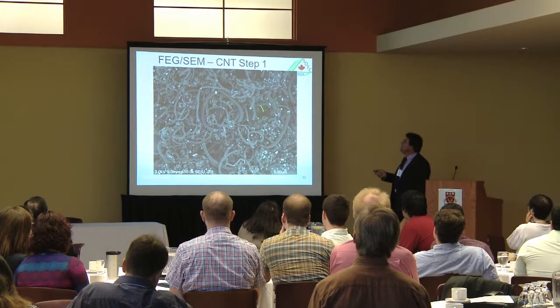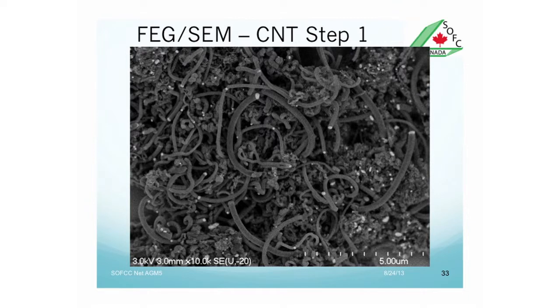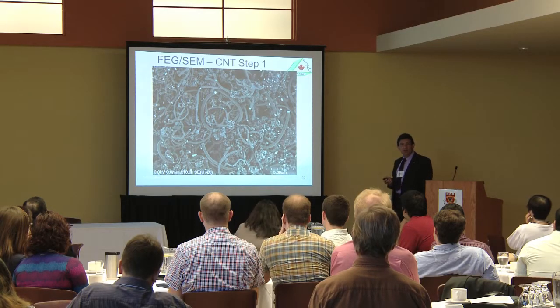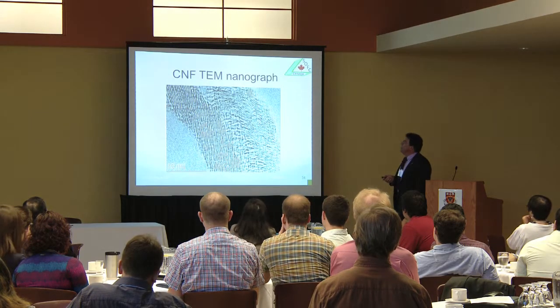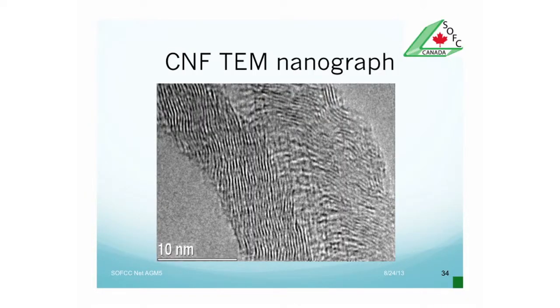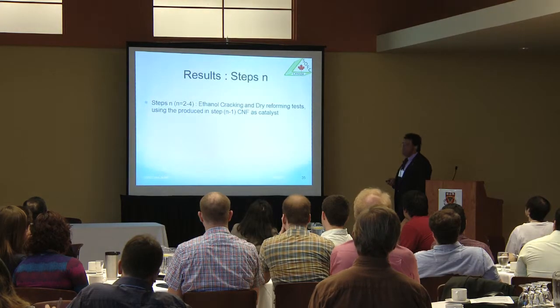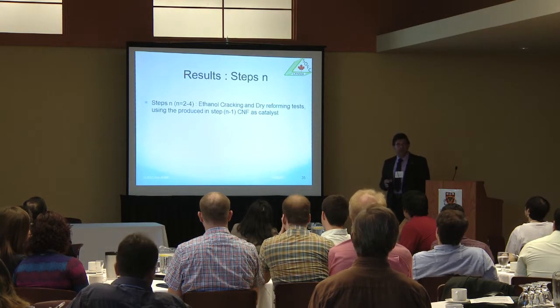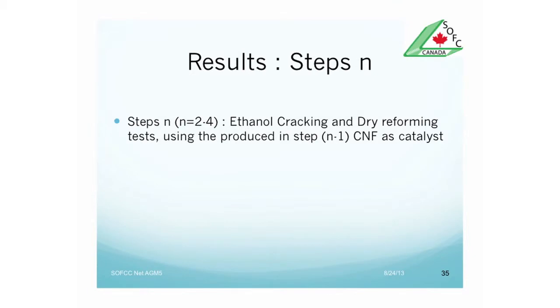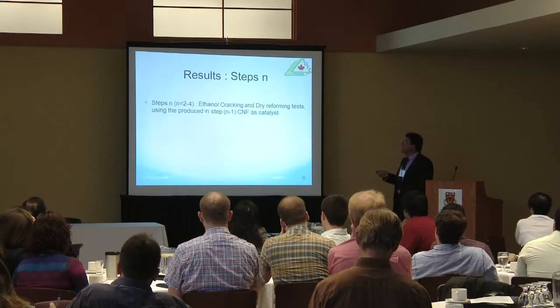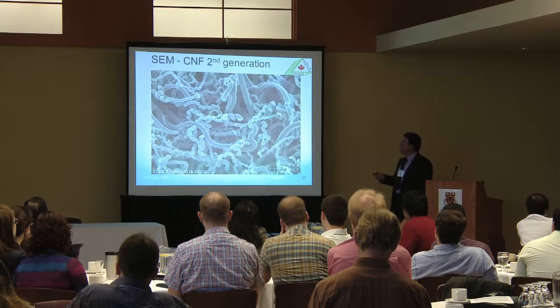So these are the carbon nanofilaments which are obtained through this process. The white spots you see here are essentially the iron carbides which are at the top of the nanofilaments. This is a nanograph showing details of the nanofilament. And we have used this type of nanofilaments only as catalysts. So ethanol cracking and dry reforming tests have been done using the nanofilaments produced in the various steps.